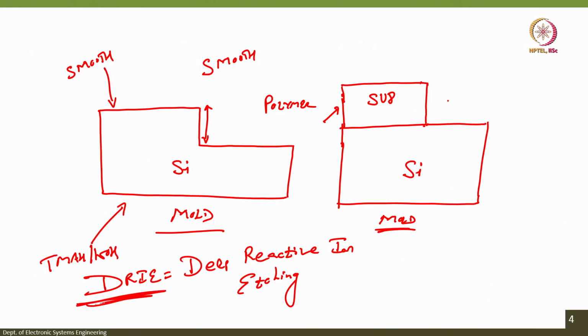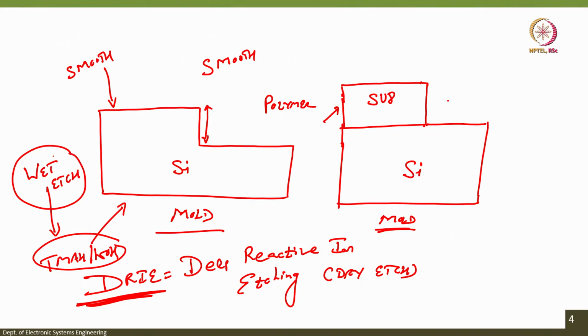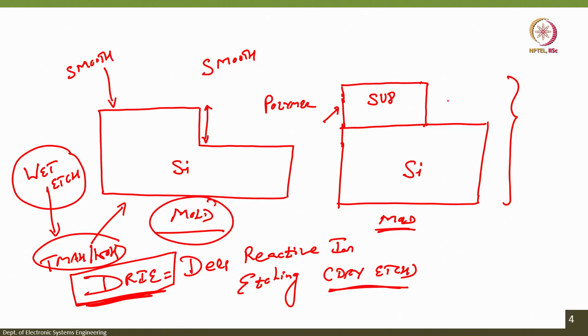When you do not have DRIE with you, see TMAH and KOH are wet etching, right, because there is a chemical involved, while DRIE is a dry etching because only gases are involved. Okay. TMAH, tetramethyl ammonium hydroxide, and potassium hydroxide are chemicals, that is why when we etch silicon with them we call it wet etch, while deep reactive ion etching using gas we call it a dry etch. All right. So, if you do not have access to DRIE, but you do have access to a photolithography system, then you can go for the SU8 mold. All right, because here you do not have to etch silicon. If you have access to DRIE, you should go for the silicon mold. Okay. So, that is a difference, that is how the PDMS patterns are created.